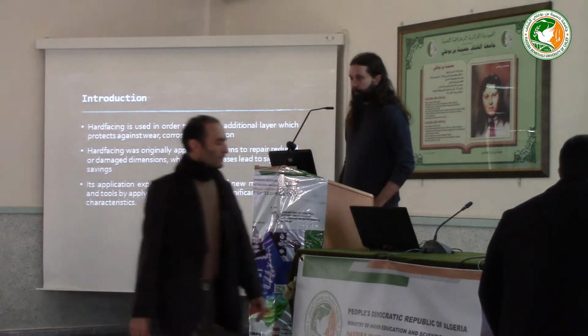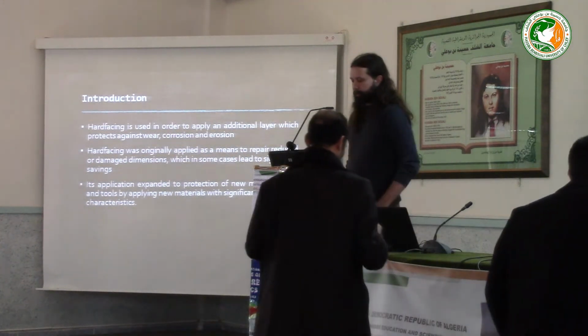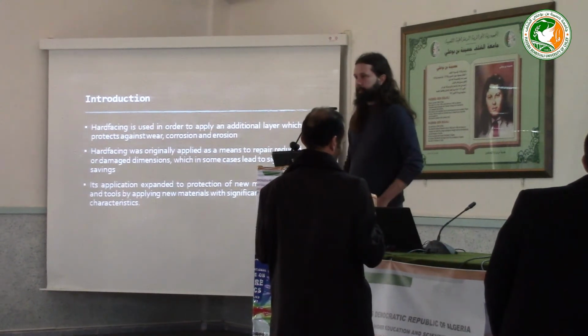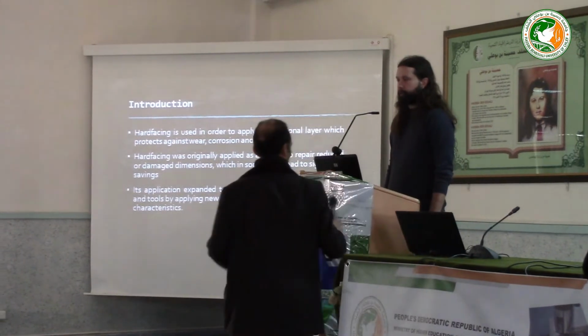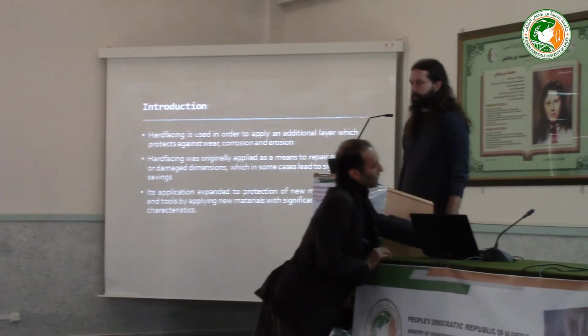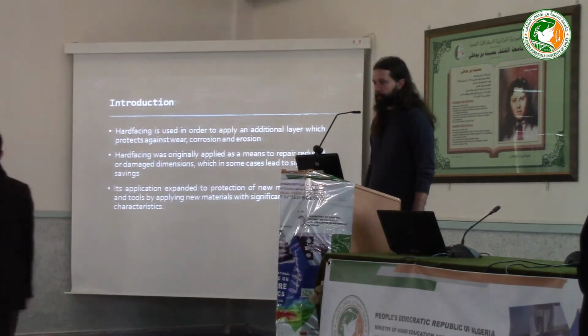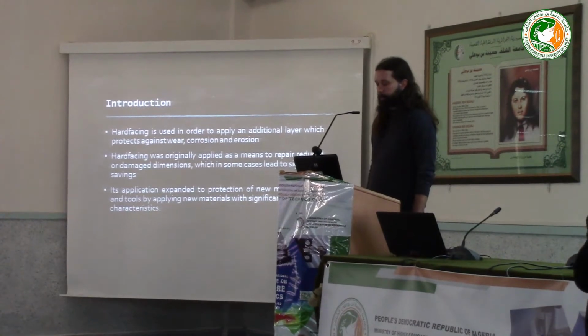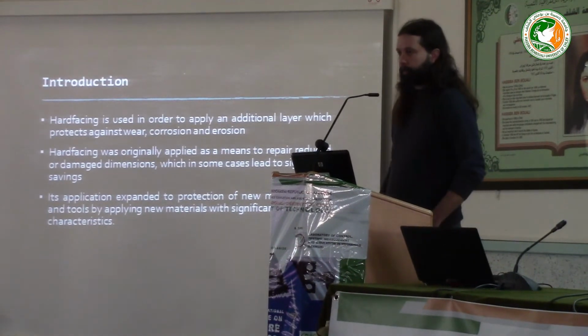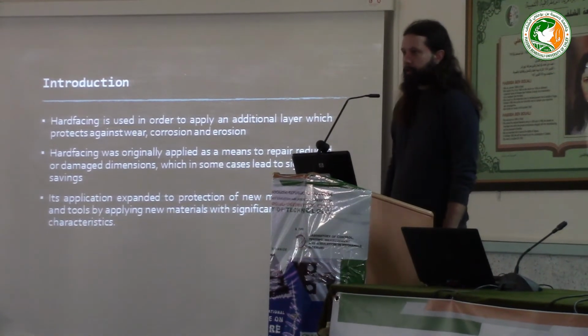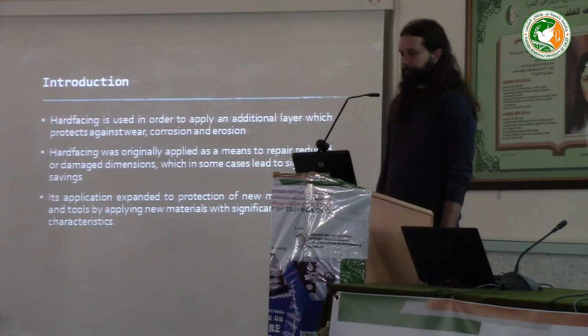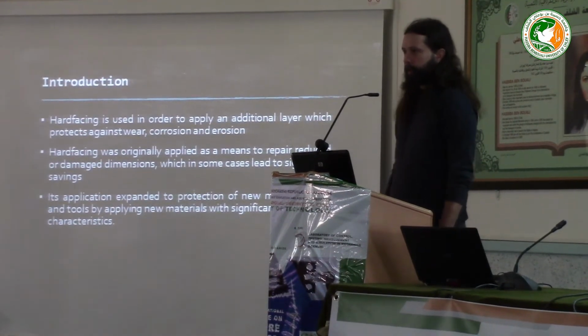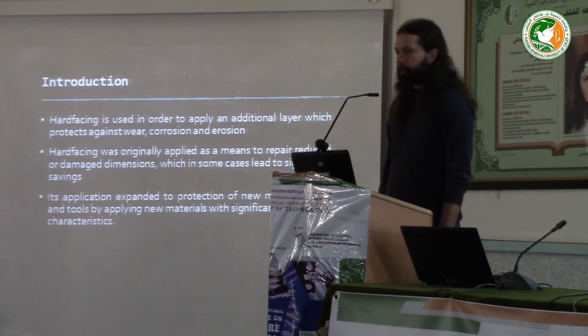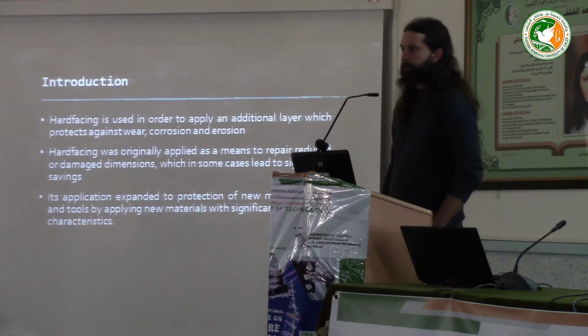Hard facing is a process that was generally used in order to apply an additional layer which would protect against negative effects such as wear, corrosion, and erosion. These effects would typically lead to a reduction and loss of dimensions of mechanical parts, which would then have to be replaced. The original purpose of hard facing was to be used as a means of repairing such dimensions, which in some cases would eliminate the need for replacement and would lead to considerable savings. For example, in one of our experiments with the crane wheel from Železara Smederevo, where repair welding technology was applied, it turned out that this made savings of around 60%.